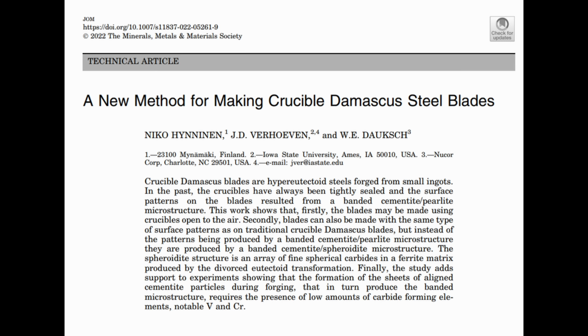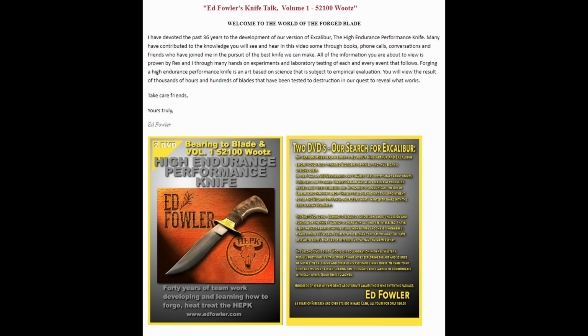So, we can try to copy the ancient material, but we can make steel in very different ways and with very different compositions and still get a banded microstructure through various processing methods. And some people have pushed the definition of this in the past. So Ed Fowler began seeing a banded structure in his 52100 because of the many low-temperature thermal cycles that he would put the steel through. So as he added more and more normalizing cycles and grain refining cycles, and he kept lowering his forging temperature, he eventually started to get a banded structure, and he started to call this 52100 Wootz. He has a DVD about how to make it. And 52100 is a pretty good choice for this because the high chromium in 52100 also increases the size of the austenite-cementite region, just like having a high carbon content does. So can Ed Fowler properly call his material Wootz, even though it's using a modern 52100 steel?